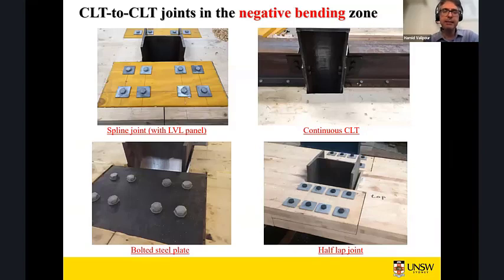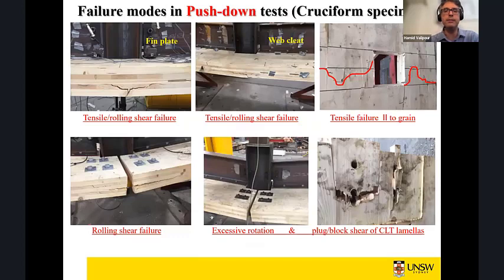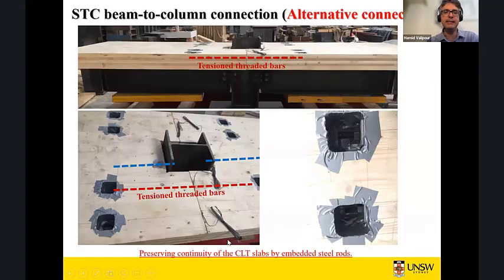And again, in terms of CLT to CLT connections, we try to use some of the connections typically used in industry for mass timber floors, like spline joints with LVL panels, like half-lap joints using bolted steel plates, and these type of connections which are easy to implement and construct. These are some of the failure modes you can see, like plug shear, block shear down the bottom on the right. You can see tensile failure, rolling shear failure in the lamellas loaded perpendicular to grain. Again, rolling shear, tensile failure, and a variety of failures happen in CLT slabs.